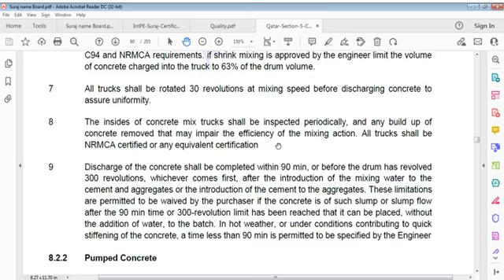whichever comes first, after introduction of mixing water to cement and aggregates or introduction of cement to aggregates. These limitations are permitted to be waived by purchaser if concrete is of such slump or slump flow after 90-minute time or 300 revolutions limit has been reached that it can be placed without addition of water. For batching in hot weather or under conditions contributing to quick stiffening of concrete, a time limit less than 90 minutes is permitted to be specified by engineer.